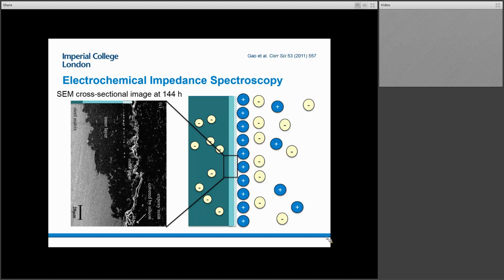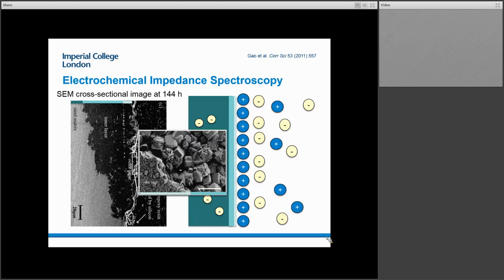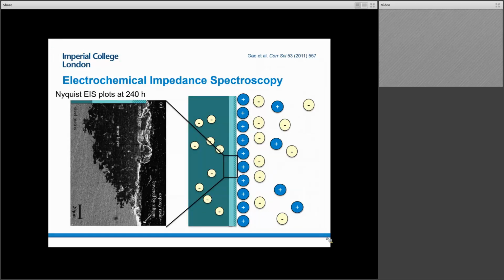And in fact, certainly near the top of the image, it does look like that new layer is quite a bit thinner. And of course, they've actually created sort of an artificial edge here to help them observe these behaviors. So that's quite fascinating. And in fact, they've taken a beautiful surface image which highlights the nature of these two layers being demonstrably different. But it's only together, the electrochemical data with these SEM images, that they were able to start to really understand the system.